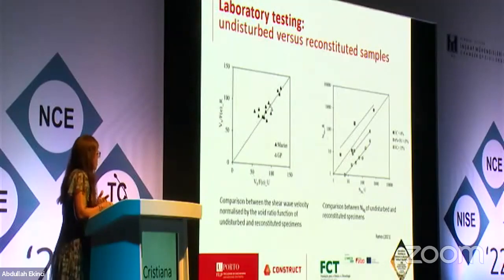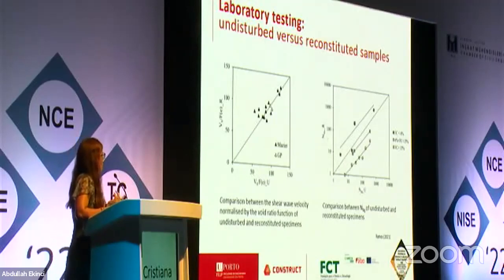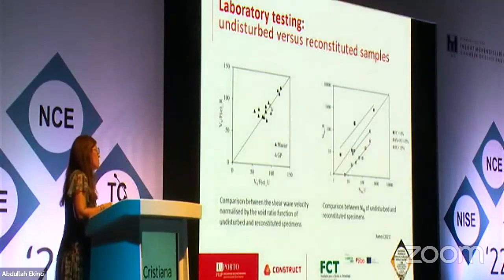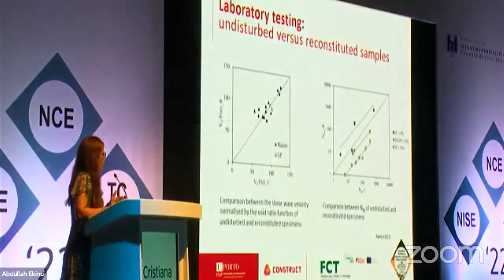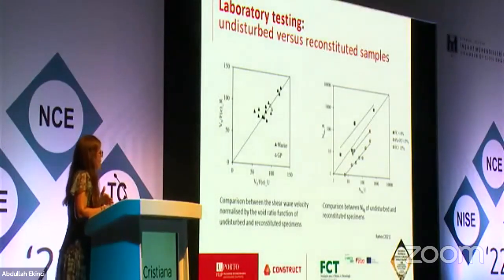And here are the results of some of the tests where we compare the shear wave velocity normalized by the void ratio function for the undisturbed and the reconstituted specimens, and we see that the distribution is quite acceptable. That means that the samples can be considered similar. And here on the right hand side, we can see that for very low fines content, the reconstituted specimen provides a slightly higher liquefaction resistance than the undisturbed ones. And the situation is reversed for higher fines content.